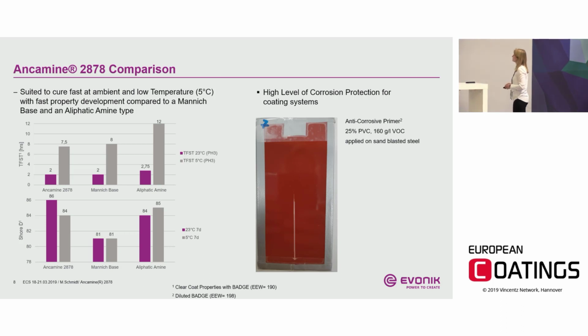So Ancamine, we also have compared with some other products. Like I mentioned before, it's an aliphatic amine curing agent, and it's relatively fast. We have compared it with the Mannich base. Mannich base is one of the fastest systems we had. If you see here the thin film set time, on the results from the drying time recorder, you can see that it's relatively comparable to a Mannich base. We have at 5 degrees Celsius around 8 hours, and at 23 degrees Celsius around 2 hours. But don't forget the safer handling and the compliant aspect, what makes the Ancamine 2878 so good.